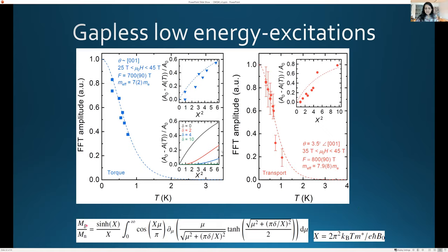of a gap system. So you can see here that what happens is that when one has a finite gap, and so delta is about 10 here, which is pretty much what you might expect for this material, you can see that there is no growth. So this is how quickly is it approaching the zero temperature limit. So if there's a high slope, it means that it's growing rapidly approaching low temperatures. And if you just see something flat, that means it's flattened and it's not growing at low temperatures. So you can see that if there's a gap, you expect it to be flat and not grow at low temperatures. As the gap size is reduced, you start seeing it begin to grow at low temperatures, until for the gapless state, the growth takes off more rapidly at low temperatures.